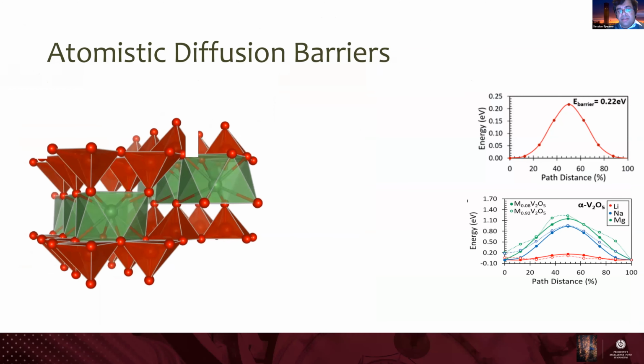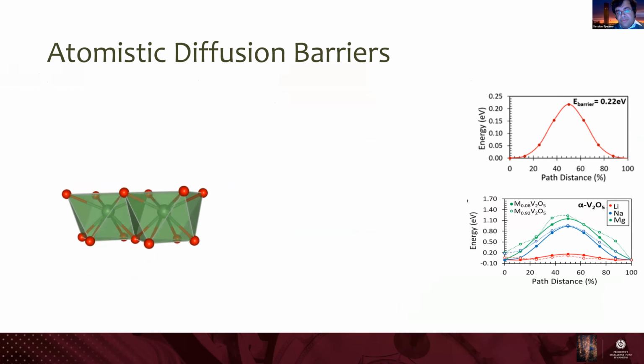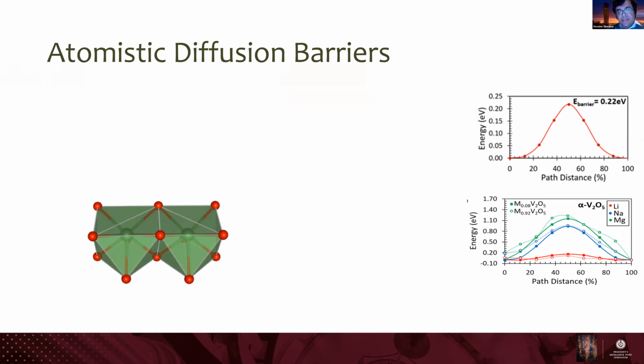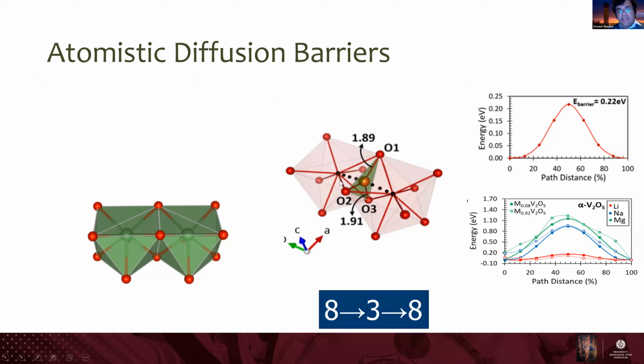So trying to understand what are the origins of some of the challenges with the system. In alpha V2O5, like you see in this animation, the lithium ions have to go from an 8-coordinated site through this trigonal planar 3-coordinated site and then into another 8-coordinated site. Okay, and this is a fairly large amount of bond breaking and bond making that must happen, and then the ion has to squeeze through a relatively narrow transition state to get to its adjacent site.